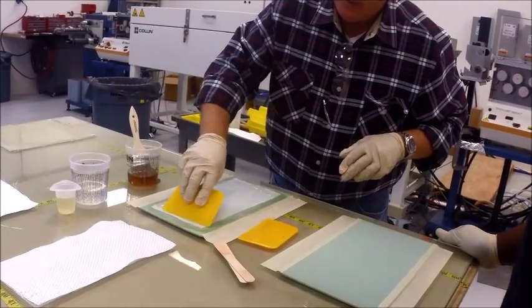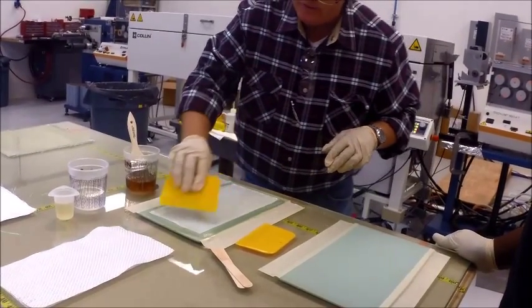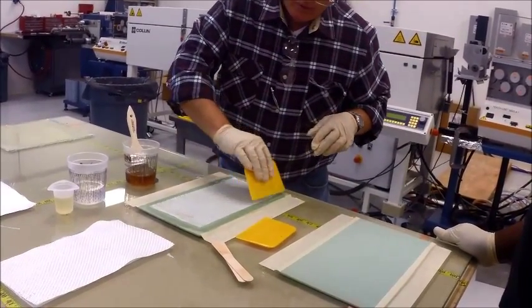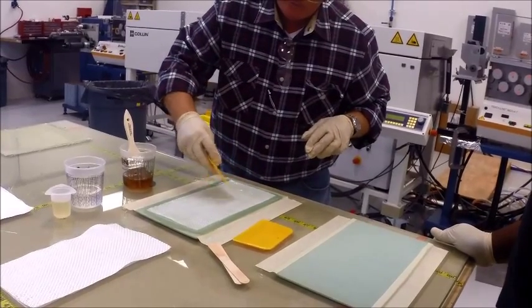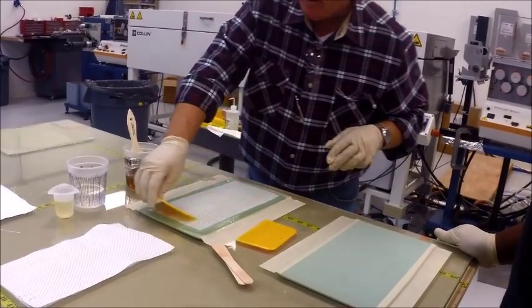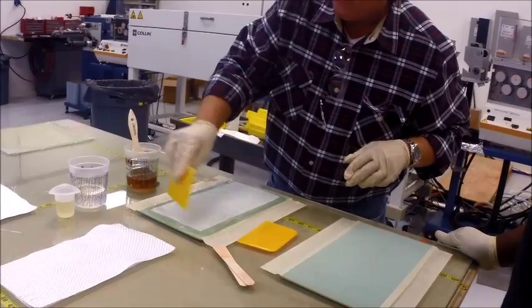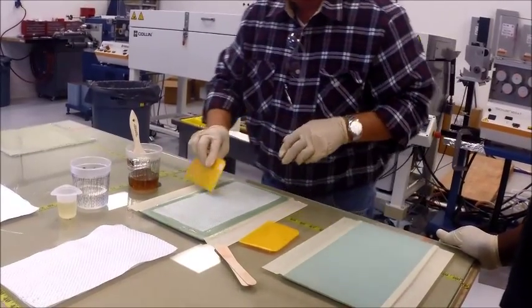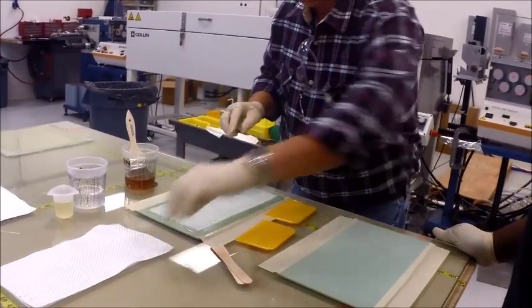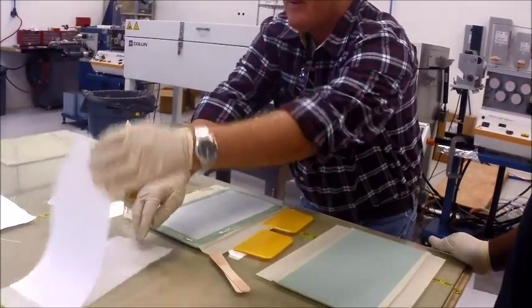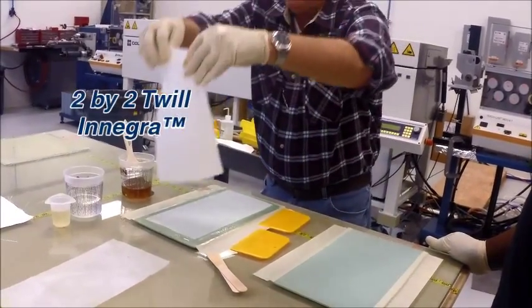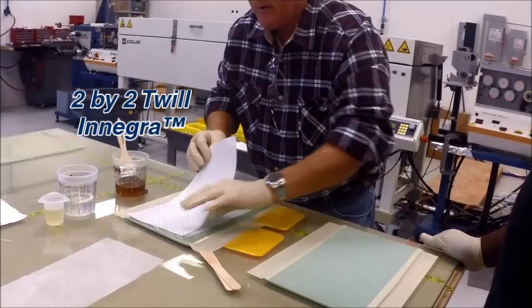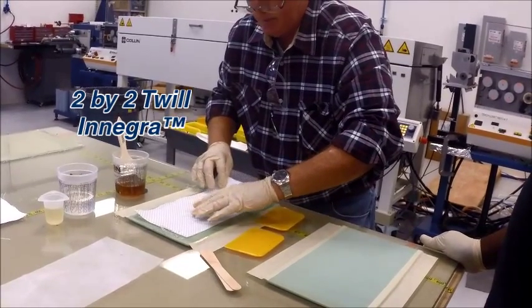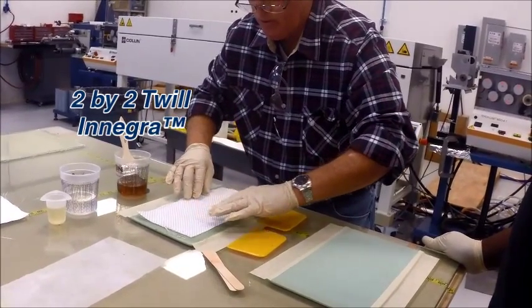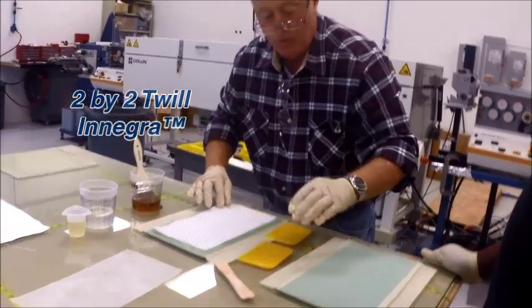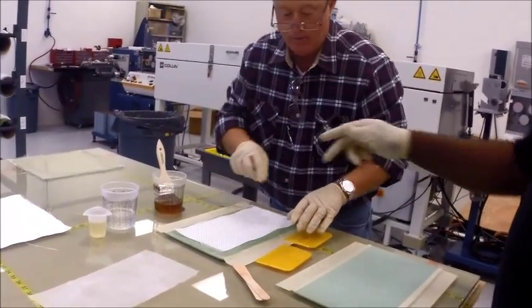This is doing a couple of things. This is pushing resin down into the core, making sure that the pores of the core are completely filled with resin so that it cannot pull additional resin out or away from the Innegra. Now we're going to apply another ply of a 2x2 twill Innegra, which would be the top surface of your surfboard or your paddleboard.